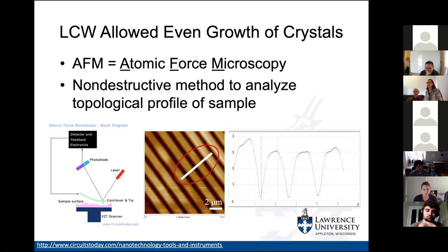Upon first glance, the crystals on the substrate look evenly spaced, with a consistent and orderly growth thanks to the LCW technique. When topological data is pulled, it only confirms this. The graph shows that the crystals in this swatch are approximately the same height and spacing apart. The crystals are approximately 138 nanometers tall and 1 micron wide. This is an important step in the research as it shows that deuterated Diisopropylammonium can be grown using the LCW technique and produce a sample that has crystals grown in neat, orderly bands across the substrate.